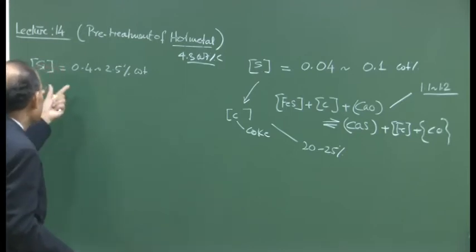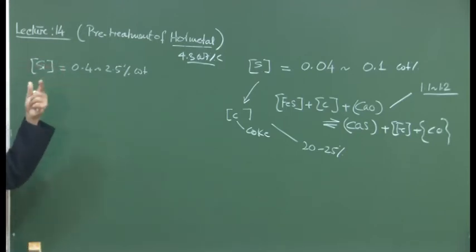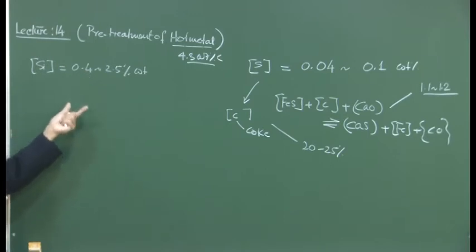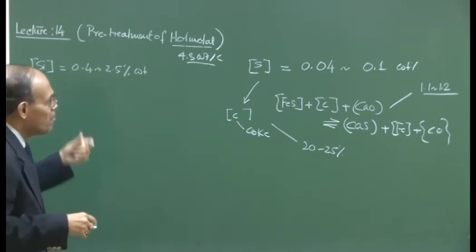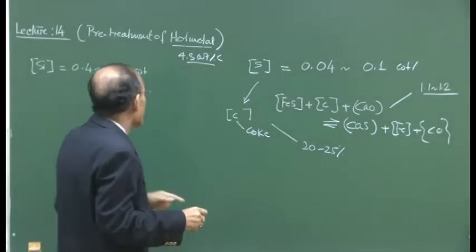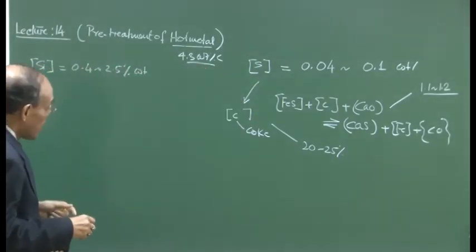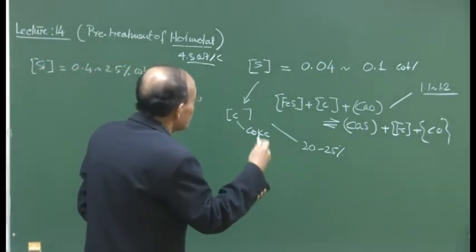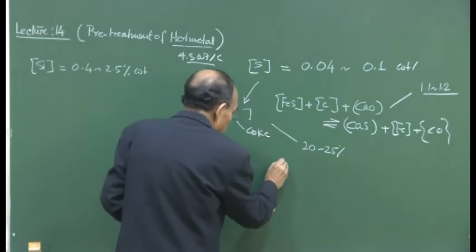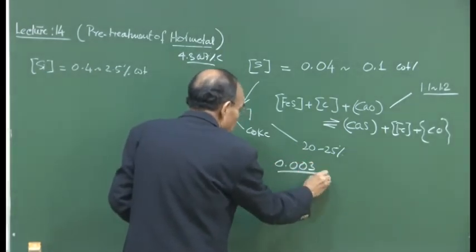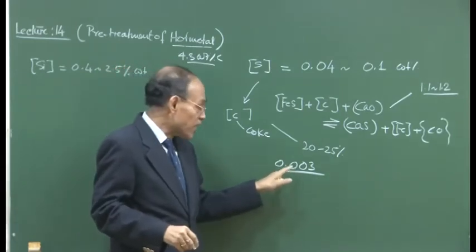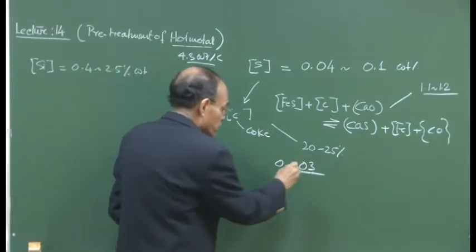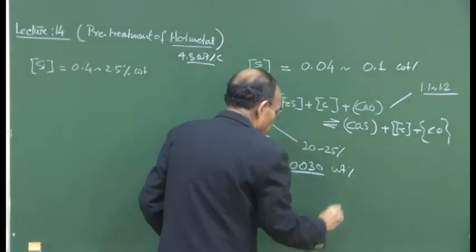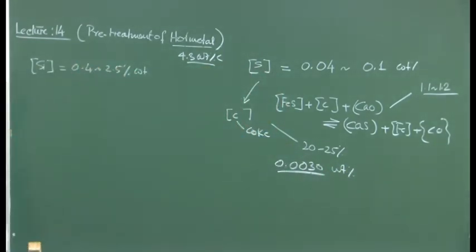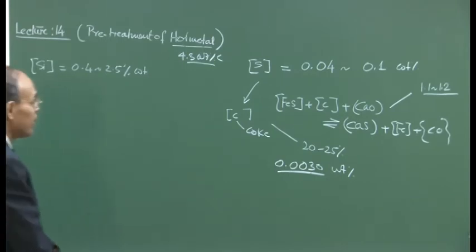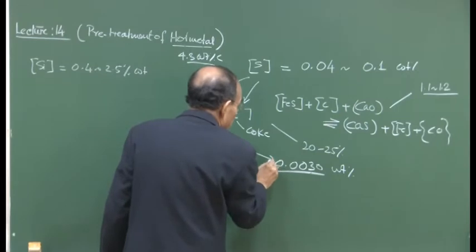And what we need in the steel making, virtually this silicon is going to be oxidized completely. So, there will be no traces of silicon left, or very little silicon left, maybe 10 ppm, 5 ppm or so. And similarly, if you do pretreatment and if your blast furnace operation is correct, and in steel making also, if you can do secondary steel making correct, then the final requirement of sulfur could be as low as 30 ppm. Weight percentage, if you multiply it by 10 to the power 4, then you get what is known as the parts per million unit. So, this is the final desirable value.